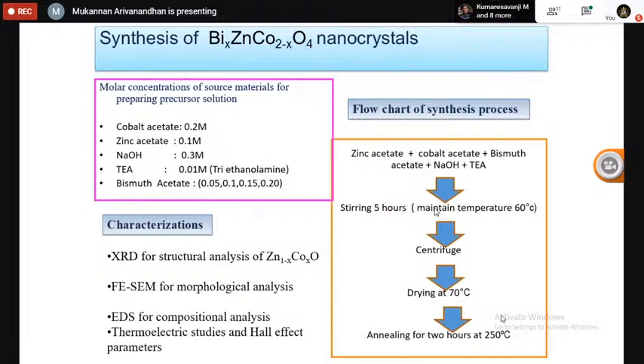So we are also working on a variety of oxide thermoelectric materials. I'll quickly go through our results, and if you have any clarifications, you can ask me, no problem. This is the bismuth-substituted zinc cobalt oxide. Zinc cobalt oxide is an oxide-based semiconductor and a rarely studied thermoelectric material. We systematically varied the bismuth substitution content at the cobalt site by properly optimizing the precursor concentrations, and this is the protocol we used for synthesizing the material.